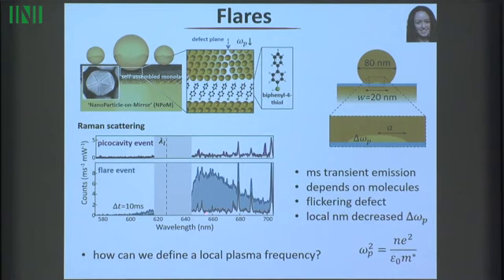So trying to understand that, we now have a theory, which is that we think this comes from the fact that you can have defects in the gold. And the defects, well, actually, we think it's probably a twin boundary, so it doesn't look quite like this. But essentially, the gold atoms maybe have a different stacking, ABC, ABC, and here CBA, CBA. So slightly different stacking. So in between, there's some sort of grain boundary. And we think what happens is the properties of the metal are different to that grain boundary. And in particular, the plasma frequency.